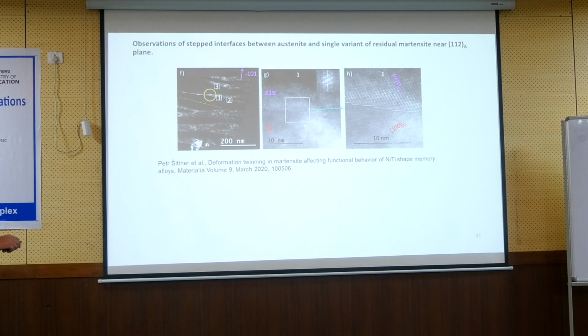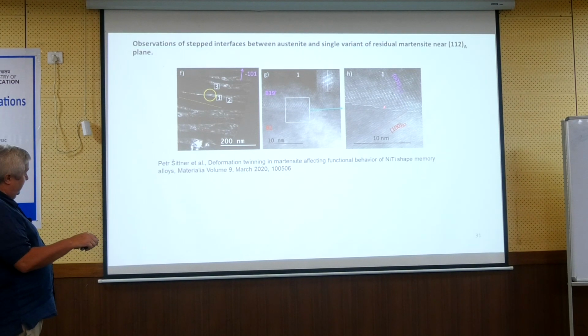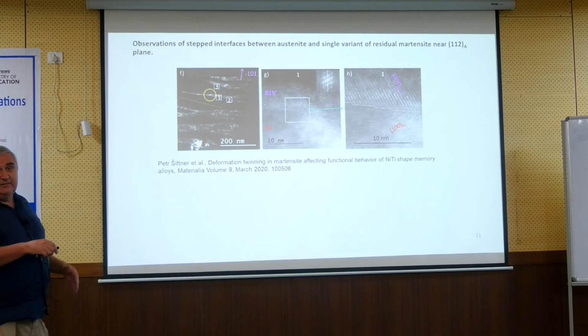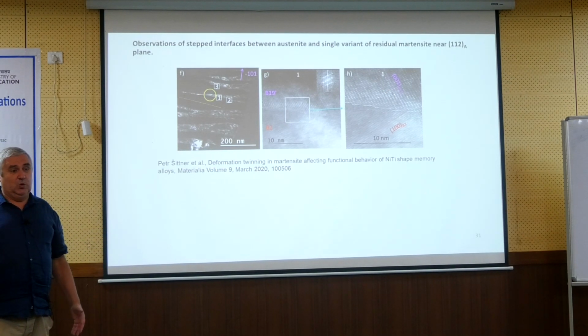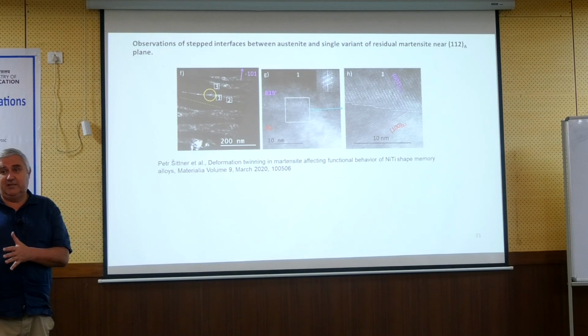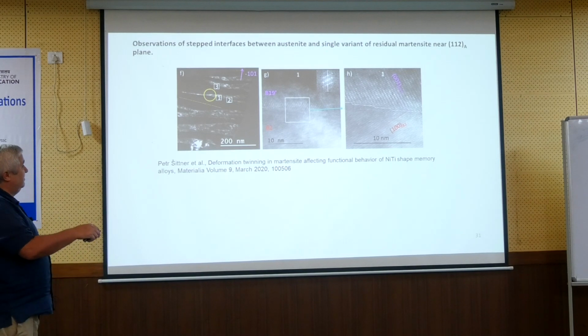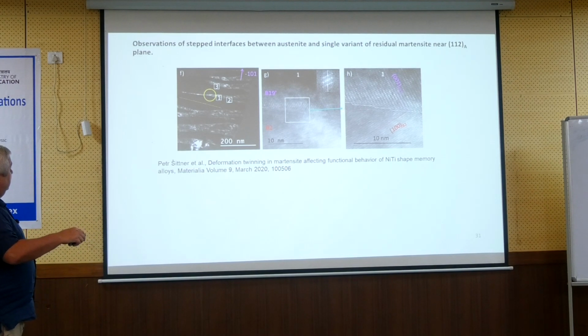But if we look by electron microscopy, high resolution electron microscopy, we clearly see interfaces which are between definite austenite and definite martensite. We see them, they exist. So the theory says it cannot exist, but every experimentator, if they look into the material by TEM, he found they exist. And somehow, so this was published in this article, but you will find it in many others.